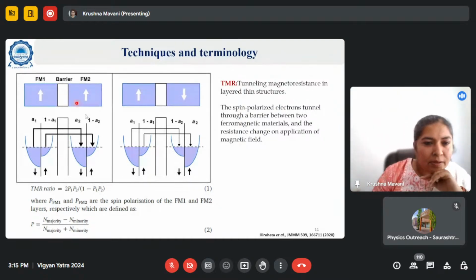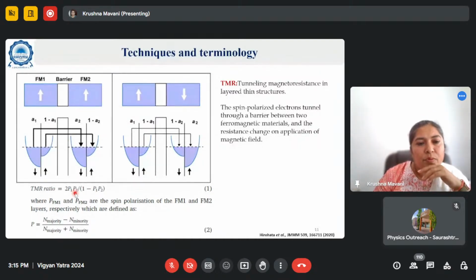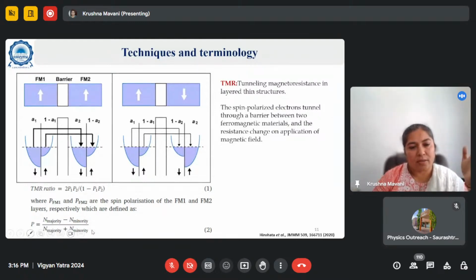So let us understand there are two situations given here. First of all, the TMR ratio can be defined. The TMR ratio is given like this, with P1 and P2. P1 and P2 are the polarizations associated respectively with the first layer and second layer here. So how do you define polarization? Polarization is the number of majority charge carriers minus the number of minority charge carriers, divided by the total number of charge carriers. Now don't confuse it with semiconductor physics. I'll tell you what majority and minority mean here.